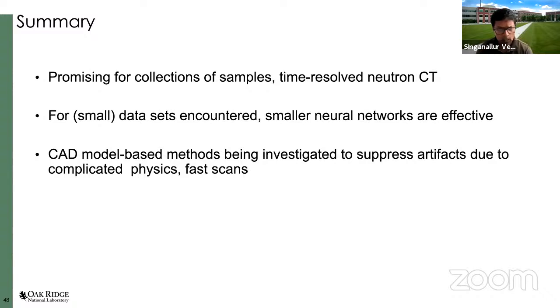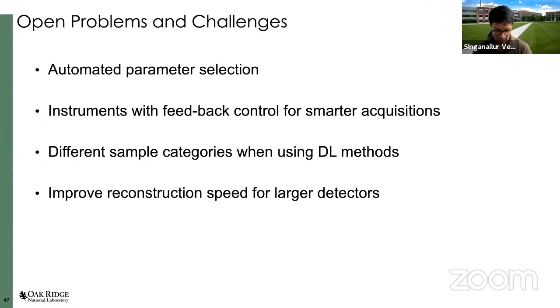So in order to summarize this little part, it's about applying neural network techniques to collections of samples and time-resolved Neutron CT. We see that it can help push the overall scan times and get fast reconstructions. For the small data sets encountered, the smaller neural networks are pretty effective. And we're investigating CAD-based models to do CT reconstructions, so to enable fast scans and also deal with all the various challenges that can occur, like beam hardening and scatter. So that concludes my talk.